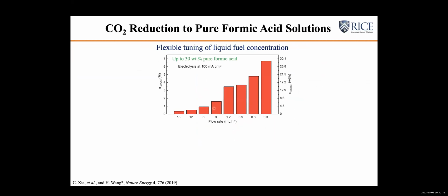Let me make sure about my time; we still have a few more minutes, okay. So let me focus on this a little bit more. Think about maintaining the production rate of formic acid by holding the current density. Now let's tune down the DI water flow rate used to flush out the product. You can effectively accumulate more and more formic acid solution. As you can see here, with slower and slower DI water flow, the maximum concentration of formic acid that we can accumulate in that work is about 30%, which is about 6 to 7 moles per liter.